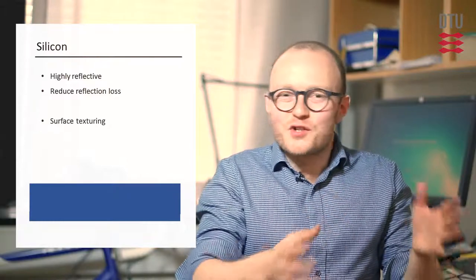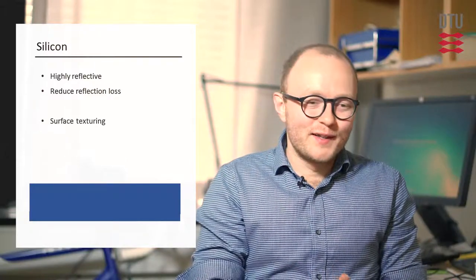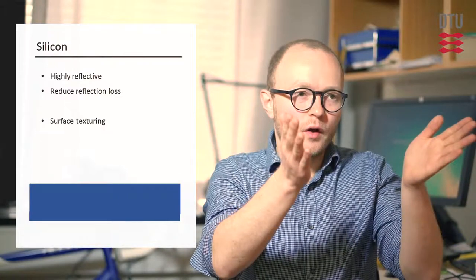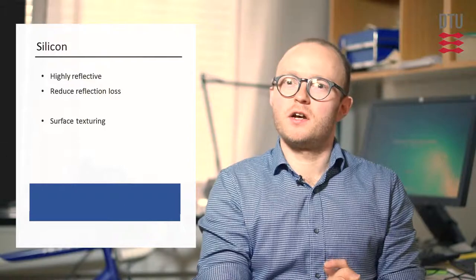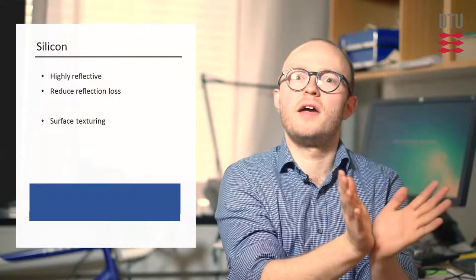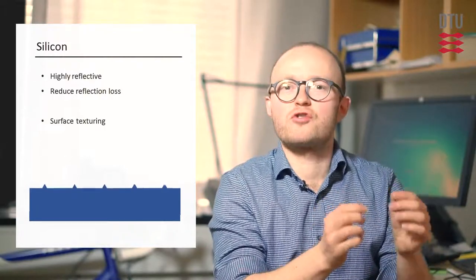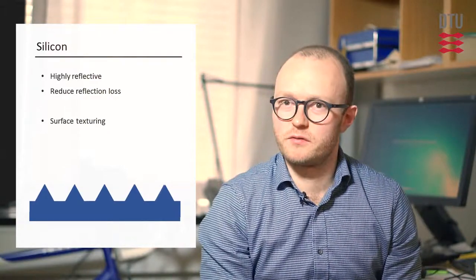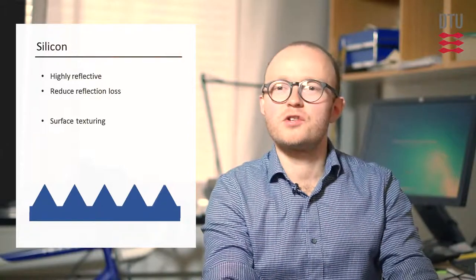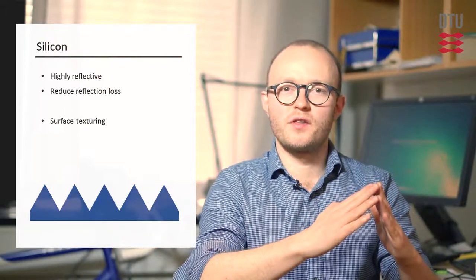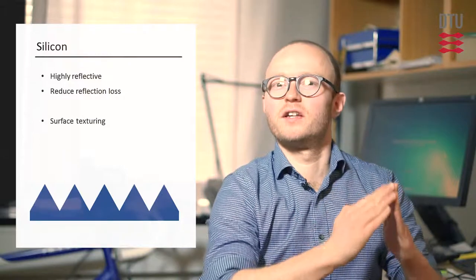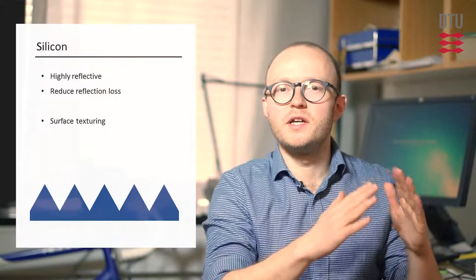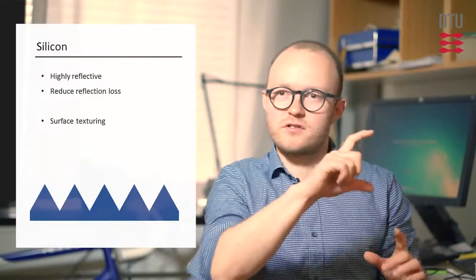At the right mixture with water and maybe a little alcohol in it, you will actually get quite perfect microscale pyramids. And those pyramids are defined by huge differences in the etch rate between the different crystallographic planes in monocrystalline silicon. Dipping it into that mixture will create pyramids with an angle that's perfectly defined by the crystal planes in silicon. And those pyramids will be on the order of 5 microns in size.